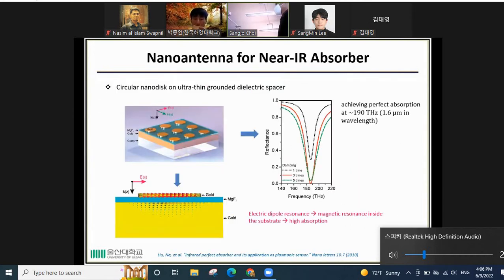Also, the nano antenna is used for a near infrared absorber. This is a circular nano disk mounted over a grounded substrate. Because of the electric dipole resonance, this electric dipole resonance creates magnetic resonance inside the substrate, and then high absorption is achieved. So we can see from this that perfect absorption is achieved at 190 terahertz, or 1.6 micrometer in wavelength.